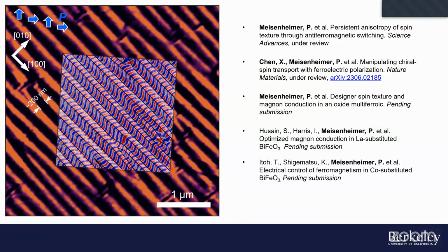In some of these doped BFO concentrations, like the 20% cobalt doped BFO, which has a pretty weak ferromagnetic moment, you can kind of see it with MFM, but it's right on the borderline. Yeah, it's very impressive. In fact, this is with Masaki Asuma's group, and they specifically did it with MFM, and then we took it and did the NV at the same location to show that their MFM is reasonable.